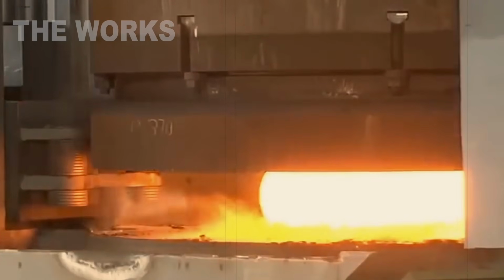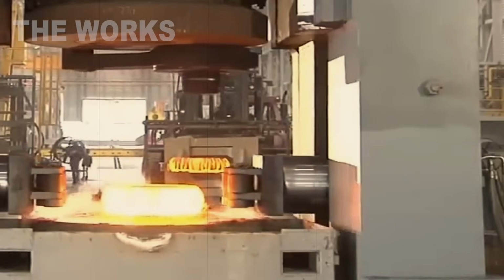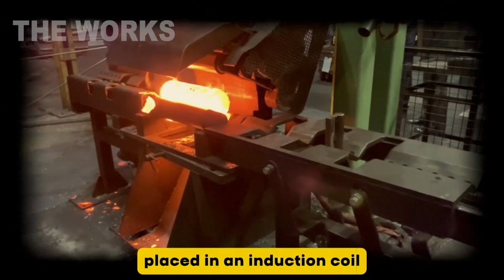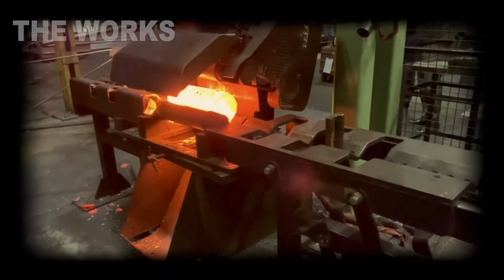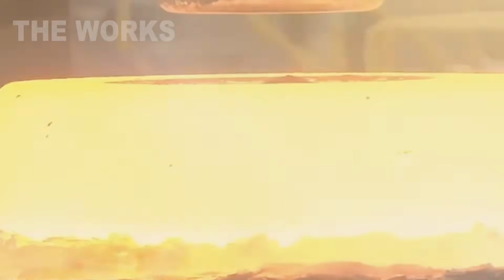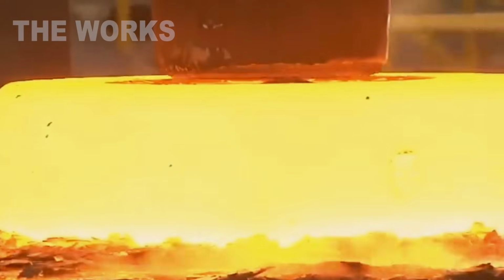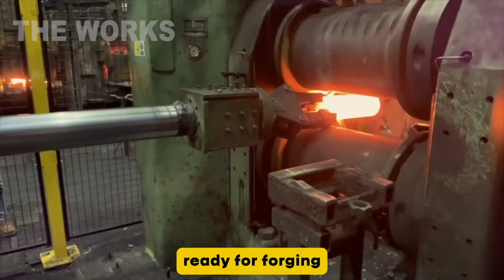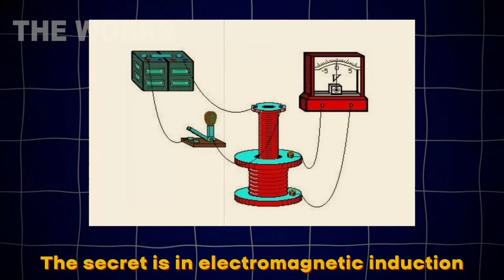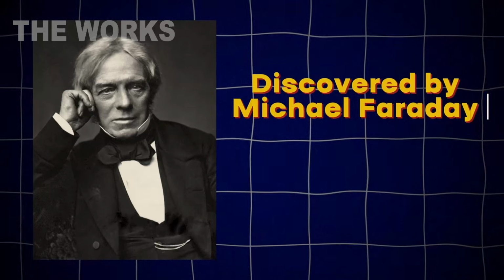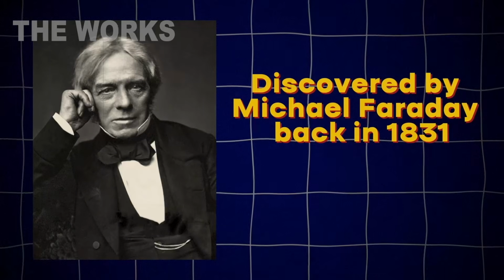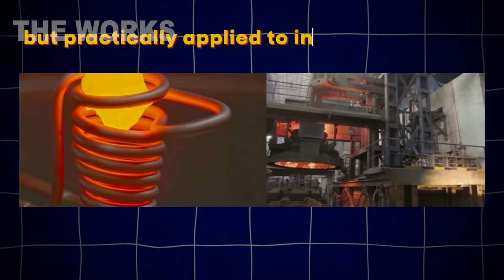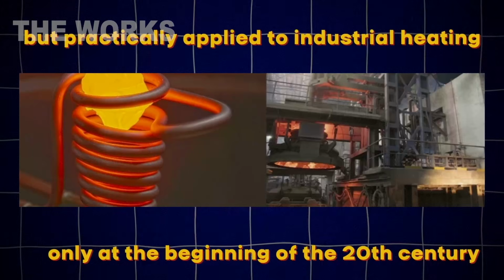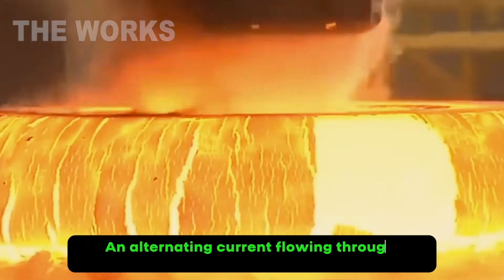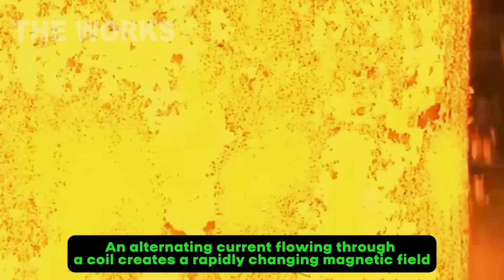No flame, no combustion, but within seconds a steel billet placed inside an induction coil glows cherry red, then orange, then that brilliant yellow-white that tells you it's ready for forging. The secret lies in electromagnetic induction, discovered by Michael Faraday way back in 1831, but only practically applied to industrial heating in the early 20th century. Alternating current flowing through the coil creates a rapidly changing magnetic field, which induces electrical currents in the steel itself, and these currents generate heat through resistance.